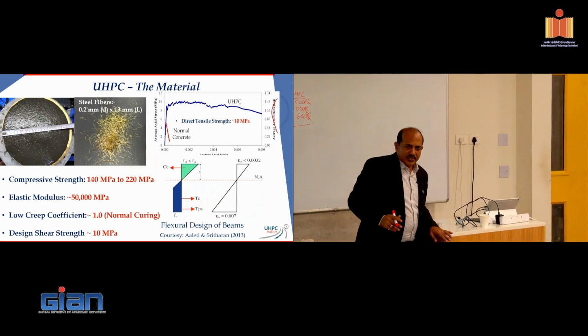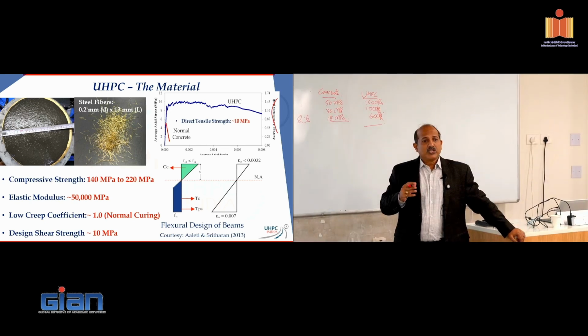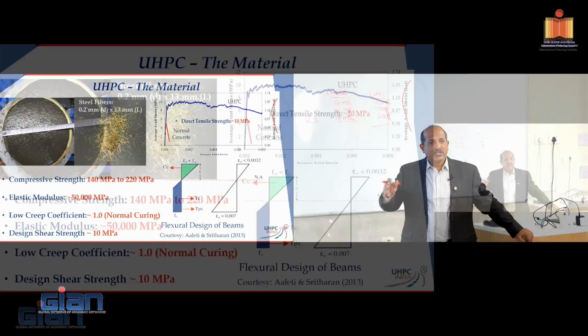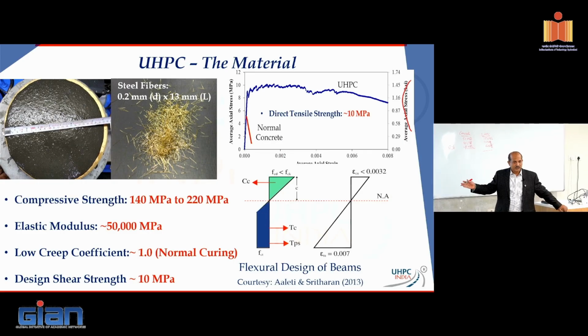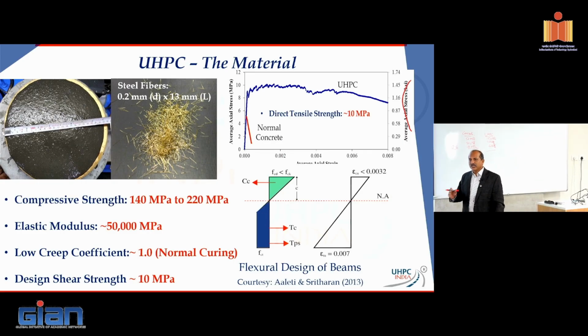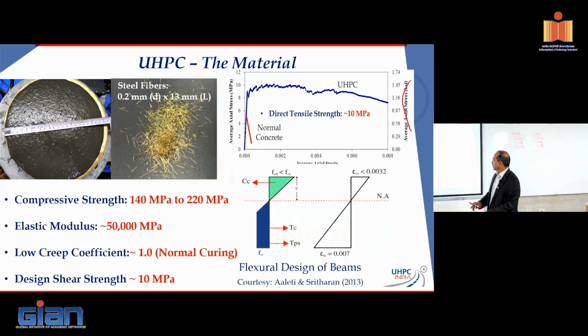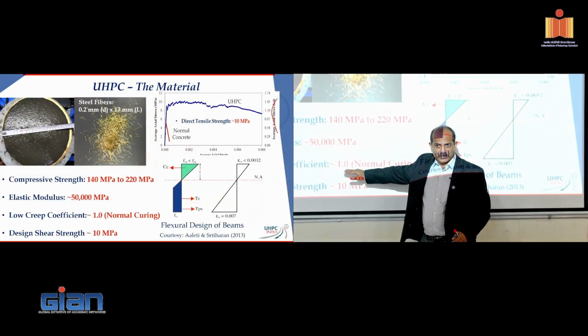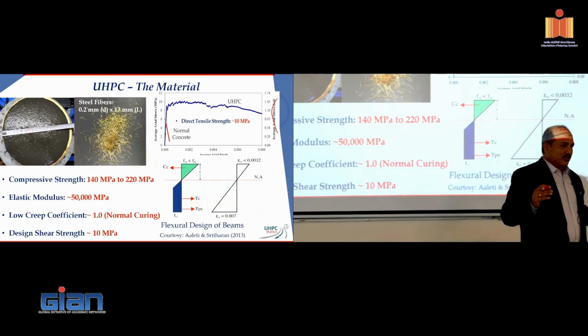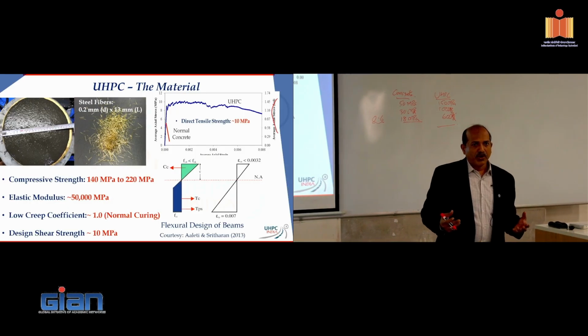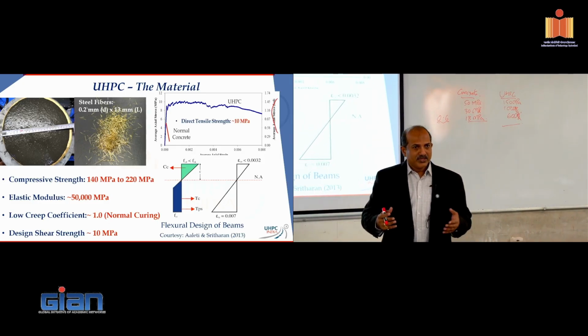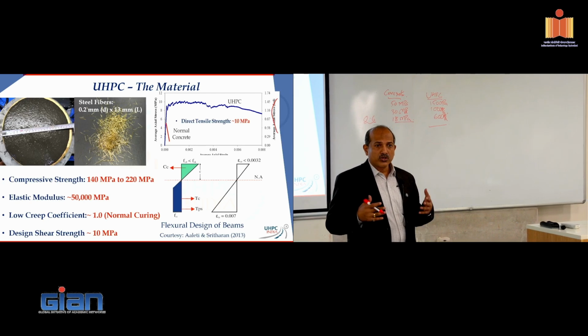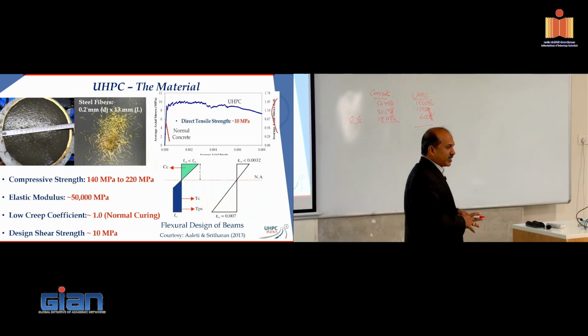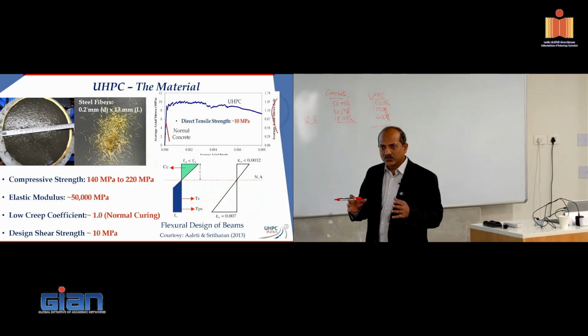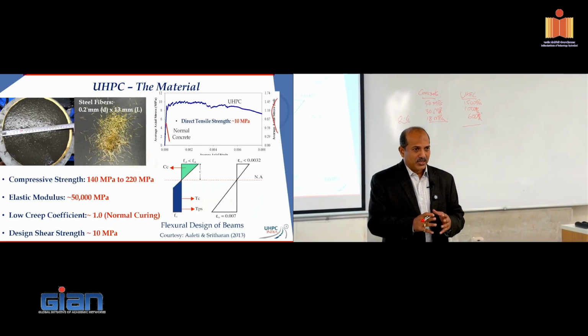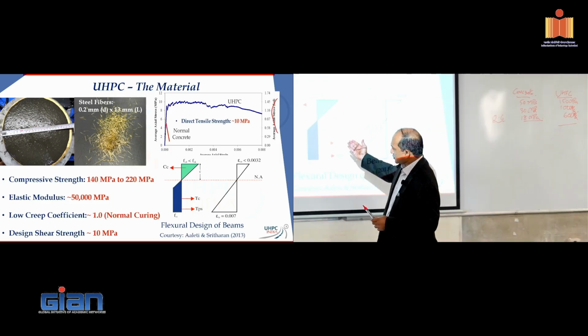Now, when I say that, that number is not limited to that. There are some special purpose UHPCs out there that can reach 75 GPa or 80 GPa as well in terms of elastic modulus, but those are not the ones which are typically used in construction. Your creep is itself lower because the way UHPC is designed as a mix, your particle packing is really, really tight. I mean, that is one of the fundamental bases of UHPC. Apart from good quality raw materials and all, the one big fundamental of UHPC is your particle packing has to be so tight so that your voids are lower, right? And so your creep automatically goes down.